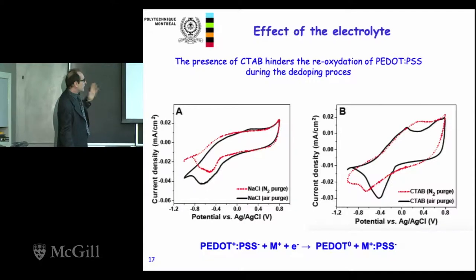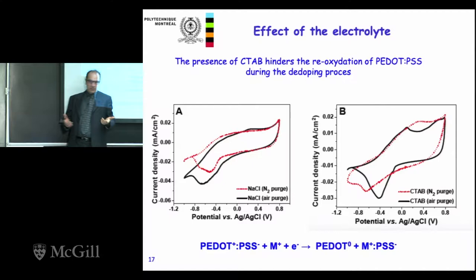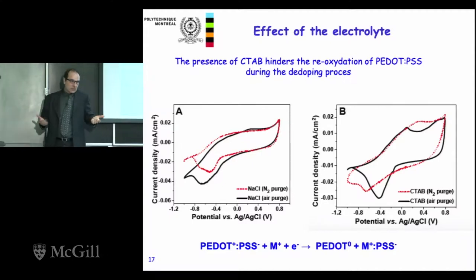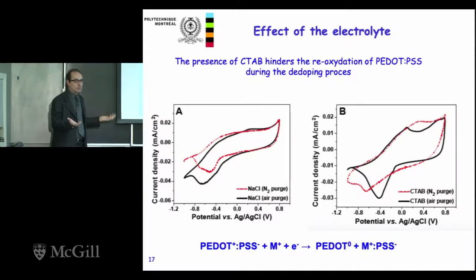Here, again, is a little bit of electrochemical characterization of our device. Again, here we compare a device in sodium chloride and a device in surfactant. And what we notice is that we operate our devices in air. We're not in a glove box because we want to use this for biological applications. And when you operate a device in air, in aqueous solution, you have a certain amount of oxygen dissolved in water.